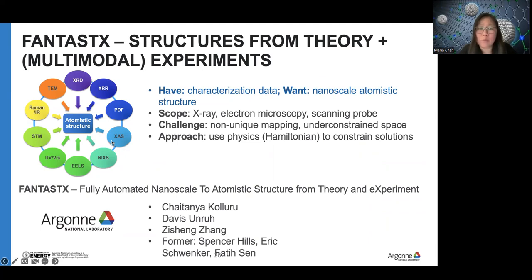A lot of times it's practical issues with the sample. In one particularly notable case, our experimental collaborators were trying to do XRD and Raman on a synthesis process. The crucible exploded repeatedly. So those are the kind of problems they have on the experimental side. But on the modeling and interpretation side, we also have an issue where the data is not always available in an equivalent way.